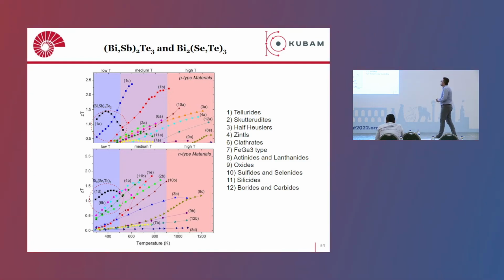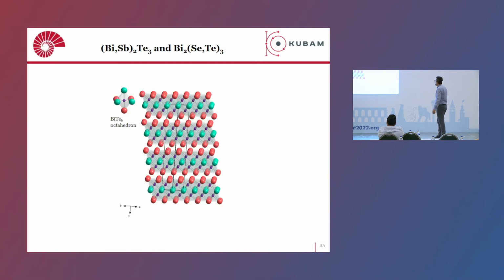We did some research also for the bismuth antimony telluride and bismuth selenide telluride. These are the low temperature materials that are mainly used for Peltier coolers. So you can see that this is the P-type, this is for the N-type materials. For the low temperature, they are kind of like the best materials. So bismuth antimony telluride, BST phase, is very good for the P-type, and bismuth selenide telluride is very good for the N-type. So the others cannot compete except for the magnesium antimonide so far.